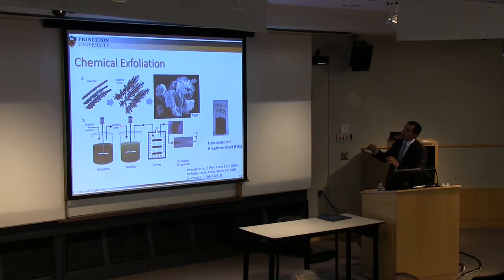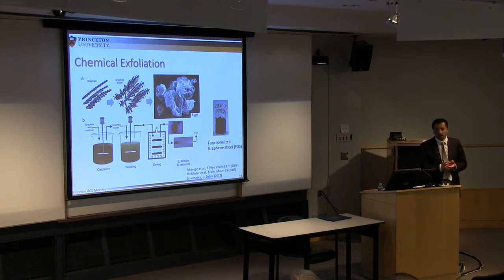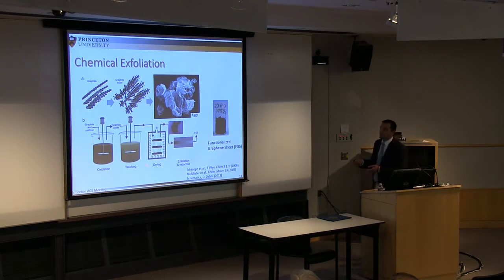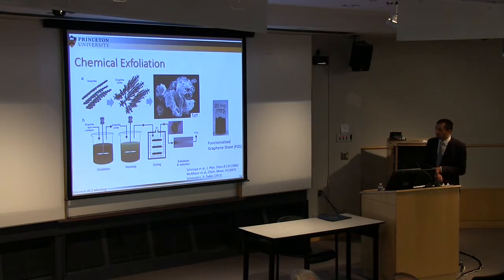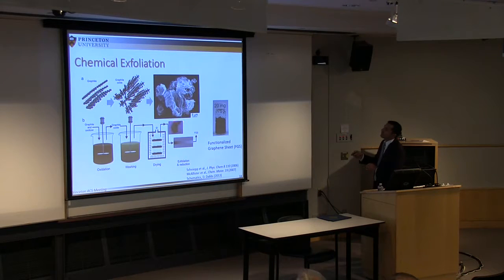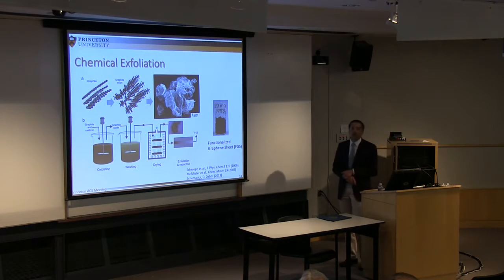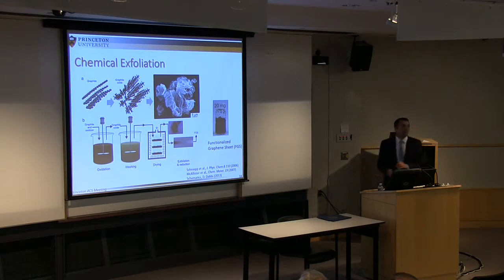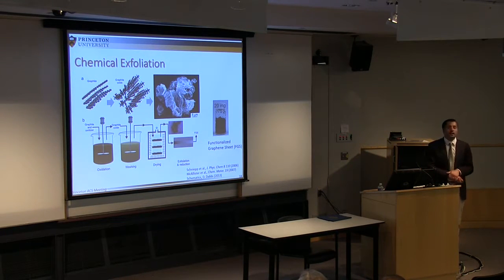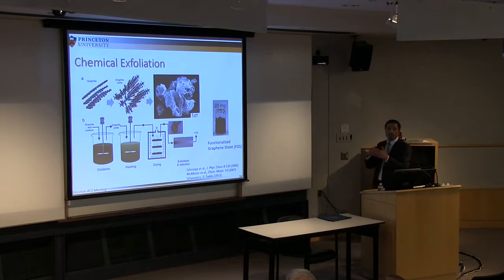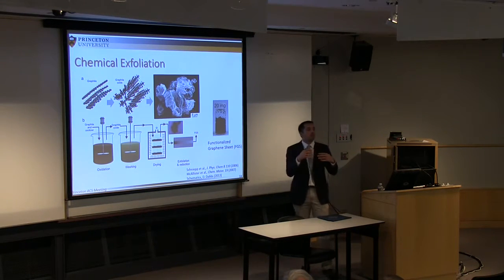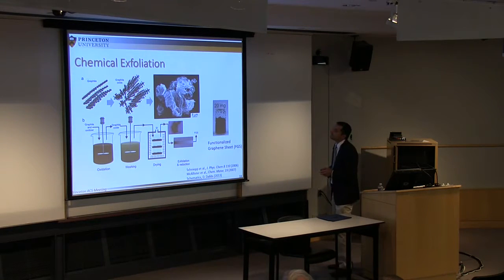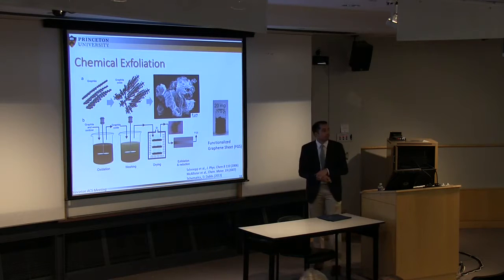We start first with graphite flakes, and you oxidize them in the presence of acids and salts. Then you carry out this reaction at relatively low temperature, about 50 degrees C, and then you proceed to the washing of this brownish suspension. And when you dry it, you obtain this brownish powder. At this stage, we call it graphite oxide. So imagine you have planes of graphene now, which are expanded with oxygen functional groups in between them. So we are not really at graphene yet.